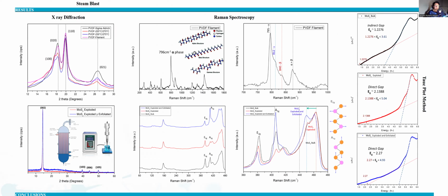So for PVDF, X-ray diffraction confirmed the presence of alpha phase, or alpha structure, which is a stable phase of the PVDF material, which has no piezoelectric properties. So we need to improve this beta phase or gamma phase, or different phases from the alpha phase, to induce the presence of piezoelectric properties of the PVDF, which is the first part of this analysis and characterization diagrams.